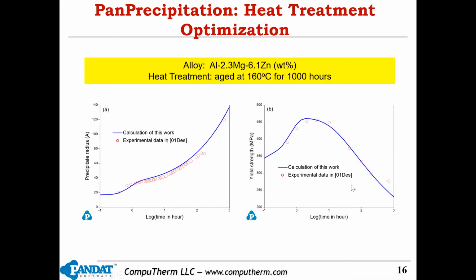In this example, we do a simulation for an aluminum alloy, a ternary aluminum alloy, and the left figure shows the particle size evolution with time, and the right figure is the yield strength evolution with time. As you can see, the particle size increases with time continuously, while the yield strength reaches its peak value and then it decreases, which represents over aging, right?